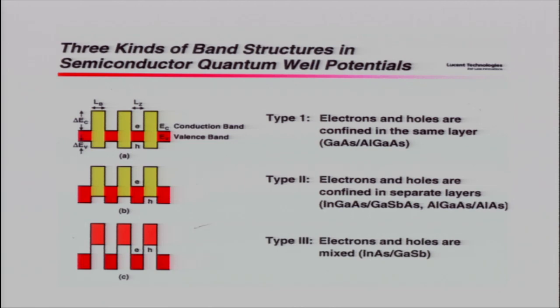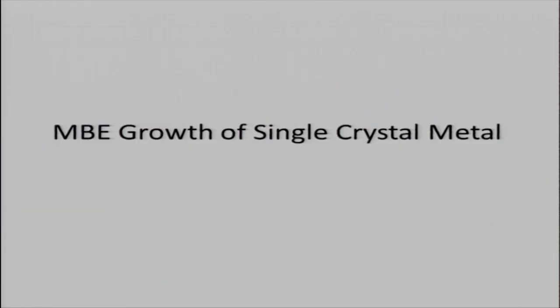As you know, superlattice structures depend on what compound you use to make them. The band alignments are different. You can align them in type 1, type 2, type 3, different alignments. One is where you can have electrons and holes in the low band gap material layer, or the electron in the low band gap material and the hole in the high band gap material, or they're mixed, depending on whether you're growing gallium arsenide, aluminum gallium arsenide superlattice structures, or indium gallium arsenide, gallium antimonide arsenide, depending on what compound you want to use.